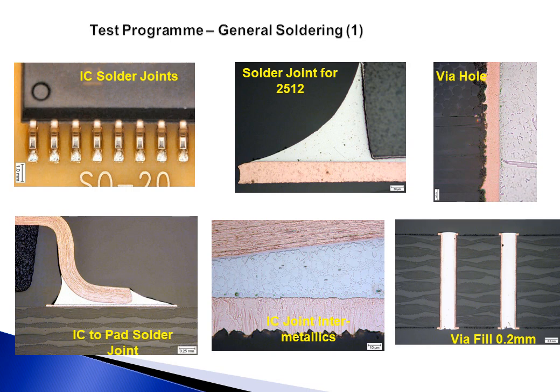So now we move on to some of the results that we got from the soldering program. You can see the typical joints for an SO20. We had joints sectioned so that you can see that there are no voids in it. You often get some voids, but no significant voids here. And it also shows that the coating has disappeared altogether where the solder's been.